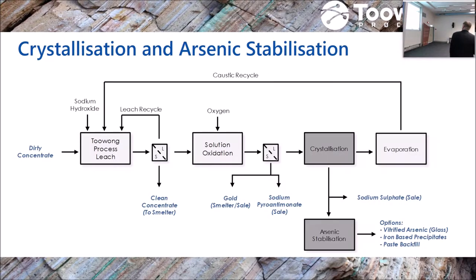Next stage, so now what's left in this solution is a little bit of silica in solution still, and obviously the arsenic still in solution. You've got sulfate there as your sulfur species. And we're basically now doing a crystallisation, cooling crystallisation stage where we pull out the sodium sulfate and the sodium arsenate, basically in a two-stage process.